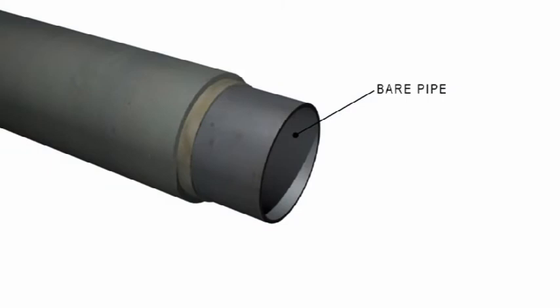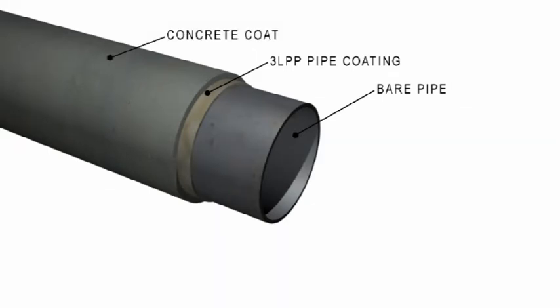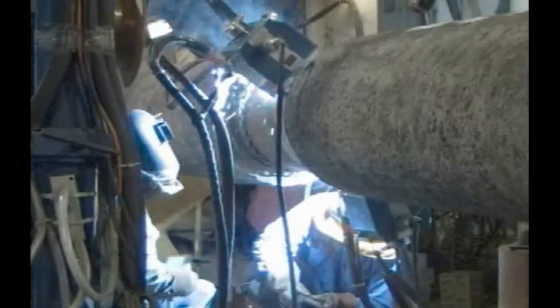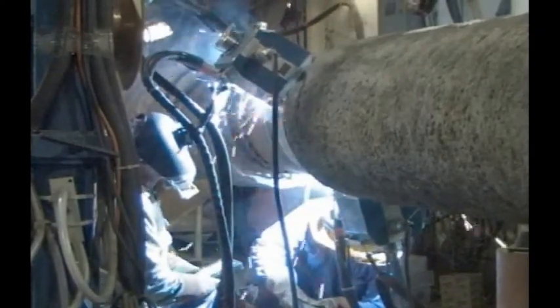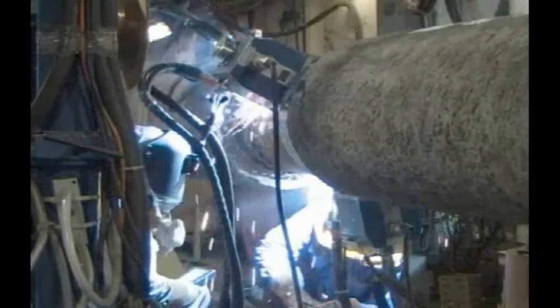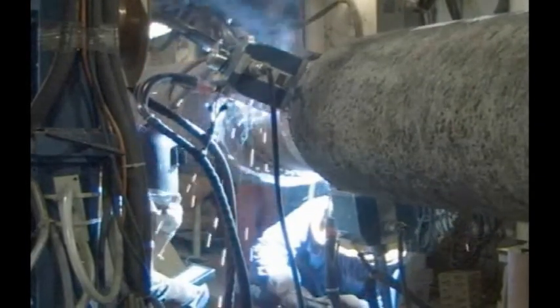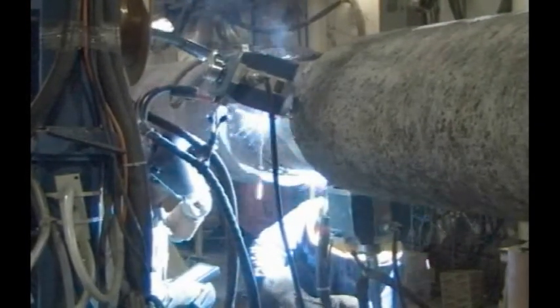The 14-inch flowline pipe is made of a 3mm thick stainless steel liner and a 17.3mm thick carbon steel pipe. It's coated with three-layer polypropylene for thermal insulation and 40 millimeters of concrete for the additional weight required for installation and on-bottom stability. Each flow line pipe section is joined to the previous one using McDermott's semi-automatic bug and band welding system. The weld is non-destructively tested using internal radiography.